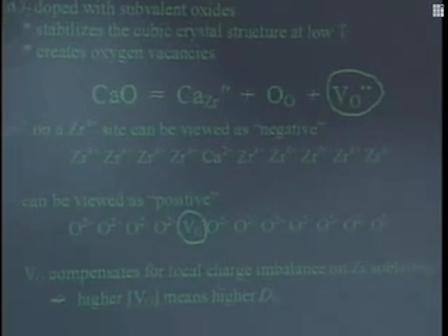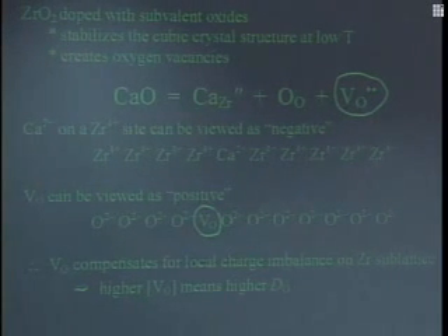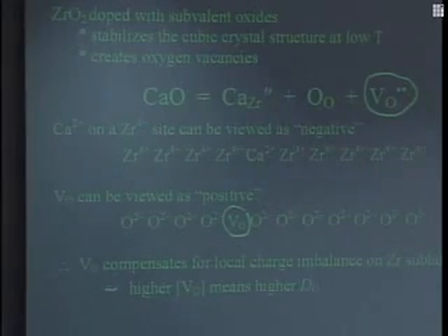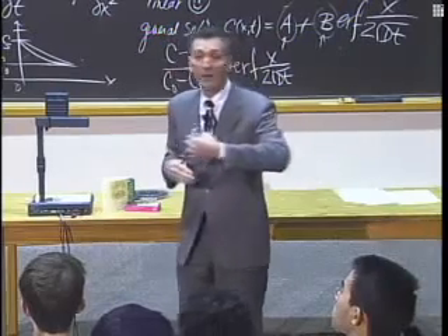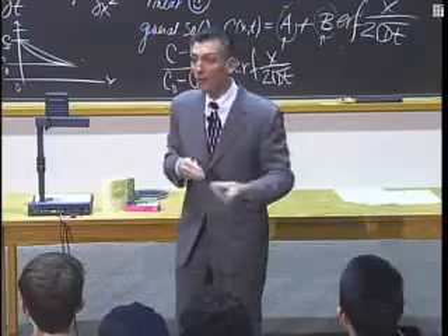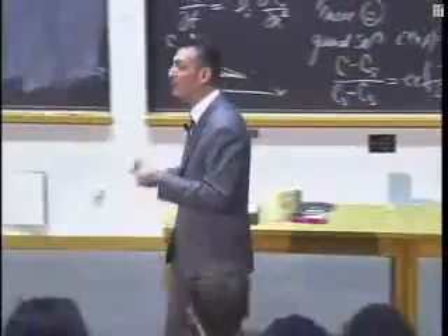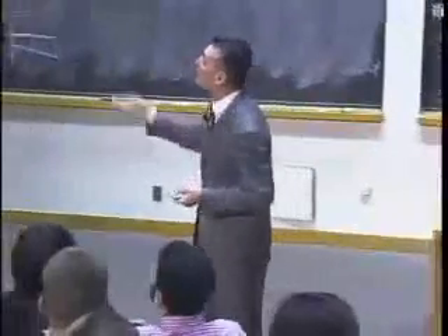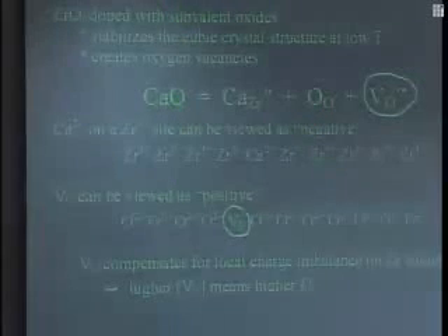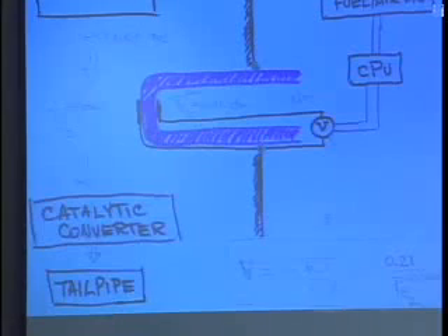So as we add calcium oxide, we make more oxygen vacancies, which means that the diffusion coefficient goes up, and that shortens the response time. It's no good having a sensor that responds on a time scale of minutes when your driving conditions are changing on a time scale of seconds. And so we dope with a subvalent oxide in order to improve the performance.